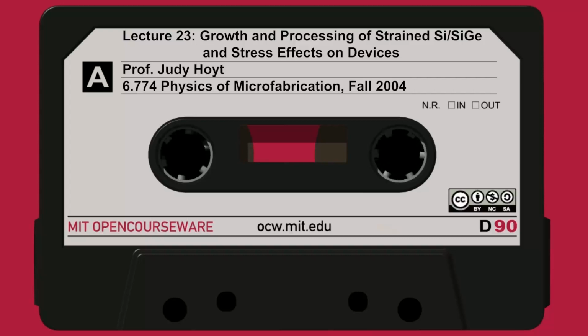So we've taken the boron diffusion coefficient, it goes down. Arsenic, which is usually very slow in silicon, now goes up. Now they diffuse about equally, which is kind of interesting. You can make some interesting device structures when you have symmetric diffusion coefficients between the N and the P-type dopant. Unfortunately, what it means is that in silicon germanium MOSFETs, we actually are much more worried about the N-type dopant diffusion because it's what's going fast, and we're less worried about the p-type dopant diffusion because the boron's going slower.